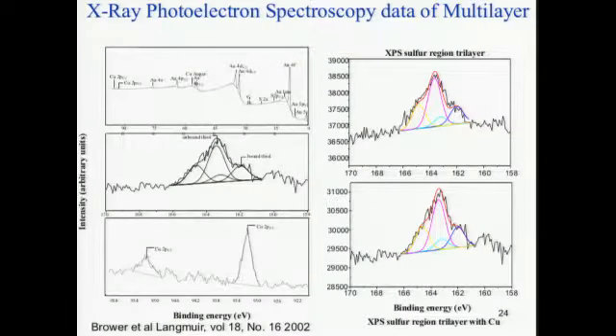And so again, looking at XPS, I found that I do not have the sandwich model that I was looking for. It was a little disappointing, but it was fun. I did make the multi-layer, and I found that instead of intralayer, where the two sulfur bonds have a disulfide bond this way, I made interlayer disulfide bonding. I know that because as I look at what we call a trilayer, and a trilayer with copper on top, I have two different sulfur peaks, or two different sulfur species. This is the sulfur region in XPS, looking at the p orbital, so there's some splitting there.